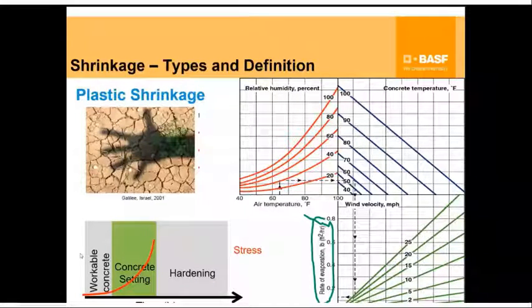However, what is critical is the stress generated by the plastic shrinkage. Is that stress higher than the tensile stress that your concrete can take at that age? Obviously when the concrete is very new, it has not built up that kind of strength, so the propensity of cracking is higher, right? The plastic shrinkage stresses are not big, but because the concrete has not built up enough tensile strength by then, you see a crack.